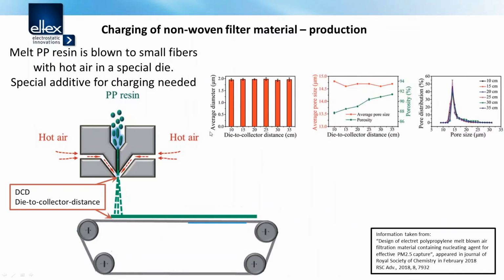The average diameter size of the fibers is almost about 2 micrometer, which is with the die to collector distance from 10 to 35 centimeter almost the same. The average pore size remains also the same, and the porosity is getting higher with a higher die to collector distance.